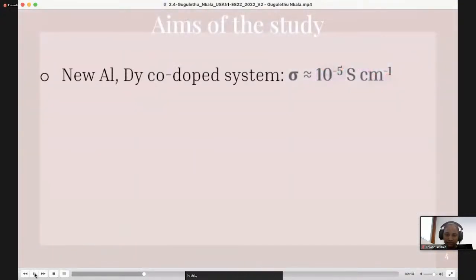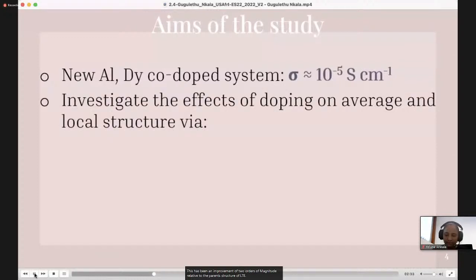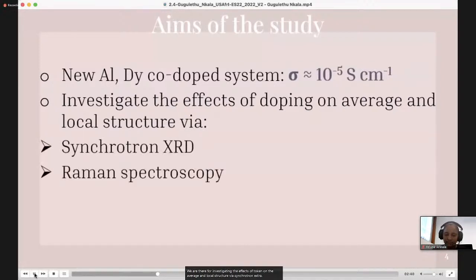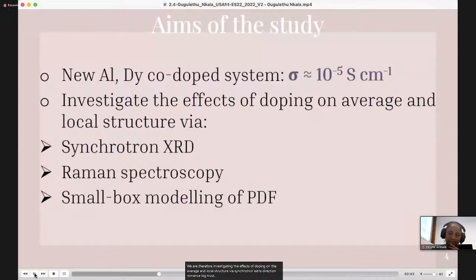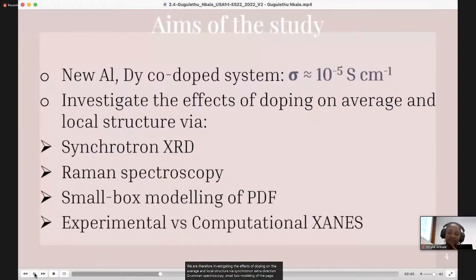In this work, we have formulated an aluminium and dysprosium co-doped LTP system, which has exhibited an ionic conductivity in the order of 10 to the negative 5 at room temperature. This has been an improvement of 2 orders of magnitude relative to the parent structure of LTP. We are therefore investigating the effects of doping on the average and local structure via synchrotron X-ray diffraction, Raman spectroscopy, small box modeling of the pair distribution function data, and experimental and computational XANES.